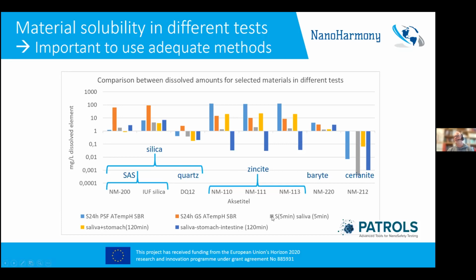And here we have in gray the 5 minutes dissolution in saliva and stomach fluid for 2 hours, and then again saliva, stomach, and intestine for 2 hours. You see that the silica materials dissolve quite a bit in the Gamble solutions, and to a lesser extent in the gastrointestinal system, as well as in the phagolysosomal fluids over here. And quartz, as expected, has lower solubility than observed for the amorphous material. In fact, it's surprisingly high and probably associated with the presence of some organic, amorphous silica in this DQ12 sample.